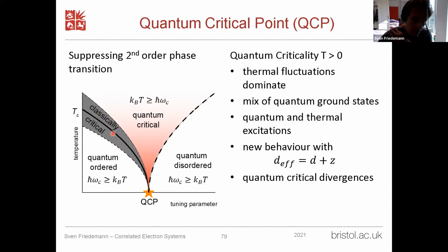So at classical phase transitions, the renormalization group behavior is what gave very good insight into what's happening there, and also describes all these exponents and universality classes. One can extend this for quantum critical behavior. What is happening in addition in quantum critical behaviors is that essentially you've got an imaginary time in the wave function, in the Schrödinger equation, that, however, acts as if it is contributing to the effective dimensionality of the system. Because on a classical phase transition, you have fluctuations happening in whatever dimensionality, and that is important because that actually bears great relevance on what universality class you're going to end up in.